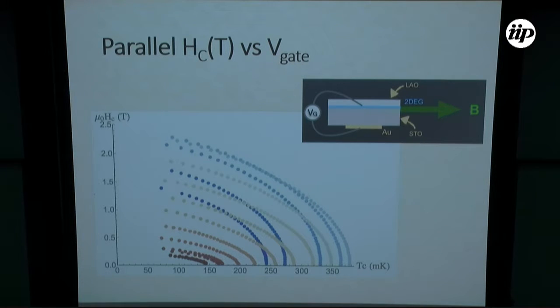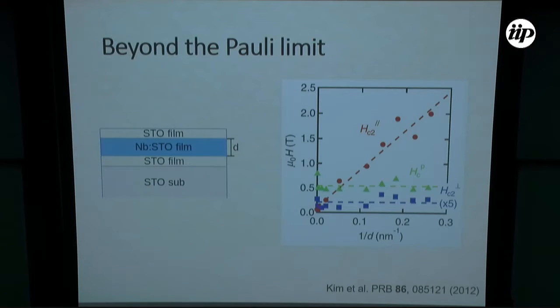somehow question the use of the Tinkham formula to extract the thickness of the superconducting gas from the in-plane critical field. This has been investigated by Harold Wang in a set of samples where we changed, by growth, the thickness of niobium-doped strontium titanate films, and he measured the in-plane critical field as a function of the thickness. So he knew by construction the thickness of the film, and he measured the field, and here is reported the relation between the critical field and the inverse of the thickness, and you see that the relation remains valid even if the parallel critical field goes beyond the paramagnetic limit.